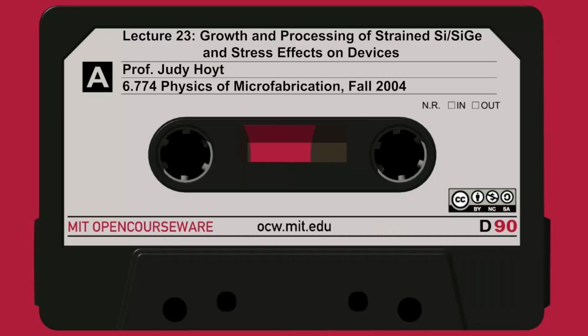On slide 38, if you're interested, I've listed a number of references on how people are trying to form relaxed silicon germanium on insulator. It turns out there are a lot of different processes, not just the bonding process. There is a SiMOX-like process where people grow silicon germanium on silicon epitaxially, and then ion implant the oxygen.